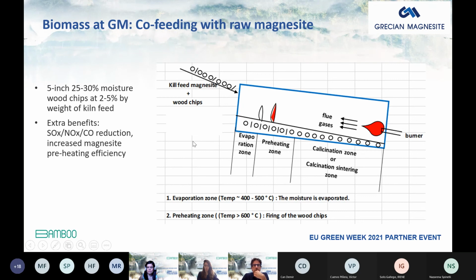There is also another mode, which is co-feeding with raw magnesite. This is a special case for the wood chips, which are large in size. For example, wood chips as large as 5 inches in nominal size, having 25 to 30% moisture, can be fed at 2 to 5% by weight of kiln feed. If this is a rotary kiln, you have the kiln feed, the magnesite, the magnesium carbonate, mixed with wood chips and fed in this direction. This goes down in the rotary kiln. At the other end of the rotary kiln, of course, there is a burner where the raw material comes into contact with the hot flue gases.